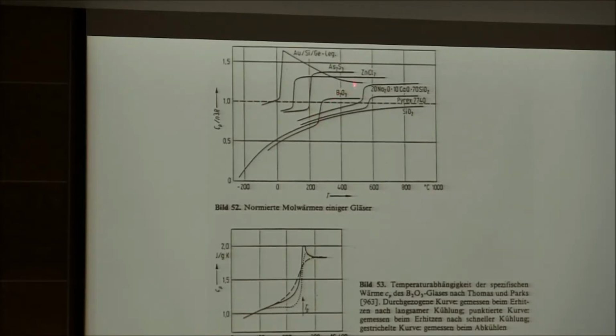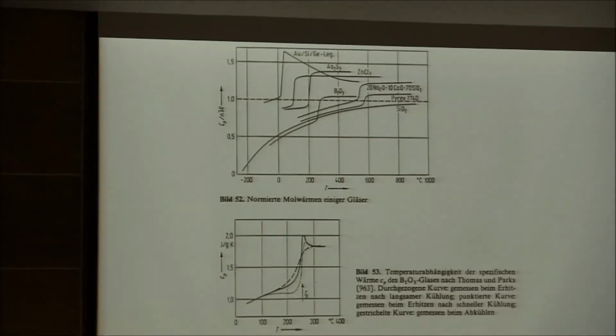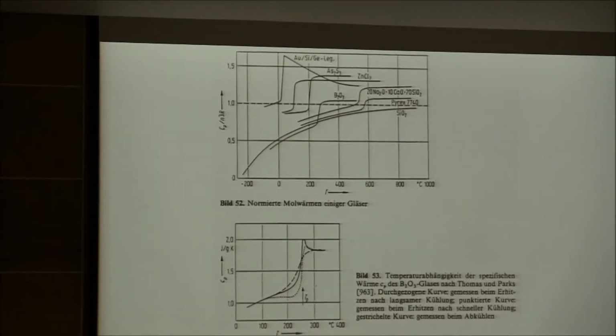Here is an example of boron oxide. You heat it up, it has a low value of heat capacity, and suddenly it has a higher value of heat capacity. The same thing for zinc chloride, the same thing for silica glass, the same thing for window glass, the same thing for metallic glass. Glasses can be made from any liquid if we can establish the right experimental conditions. So all of these show this jump in heat capacity, and this jump in heat capacity is the glass transition. And the reason that the heat capacity jumps is because you're going from a solid-like behavior of the melt to a liquid-like behavior of the melt.